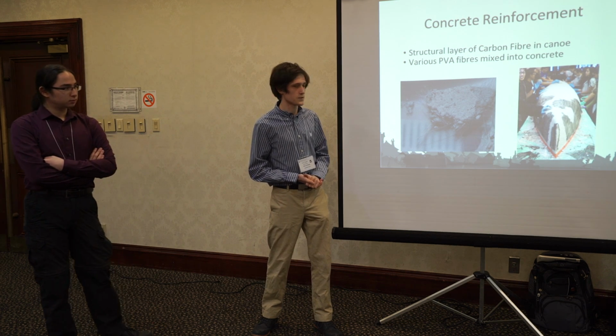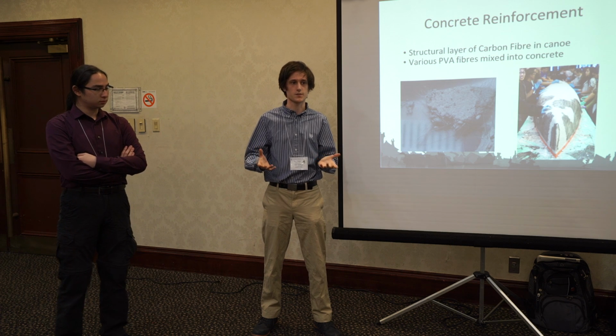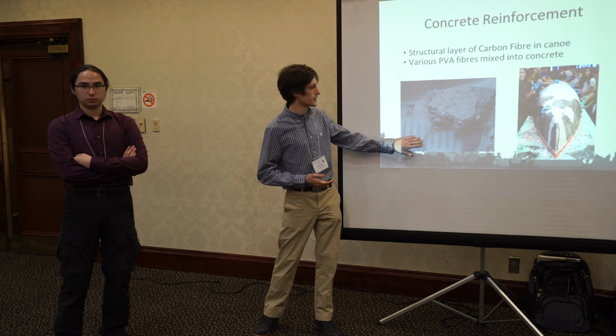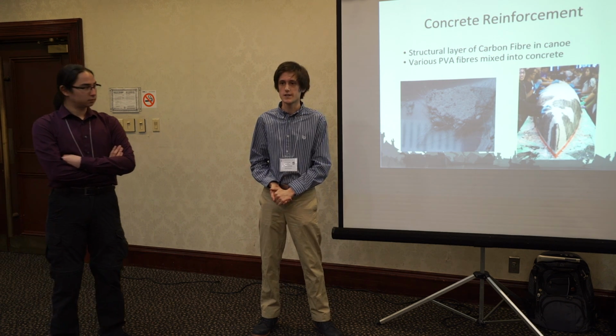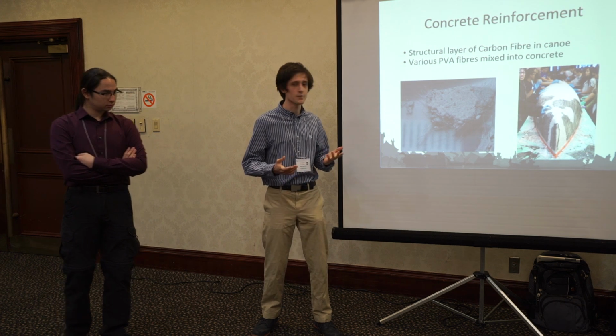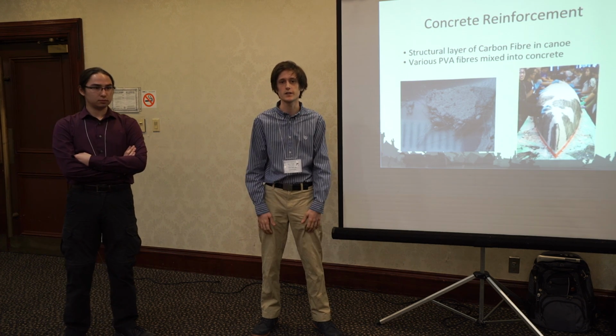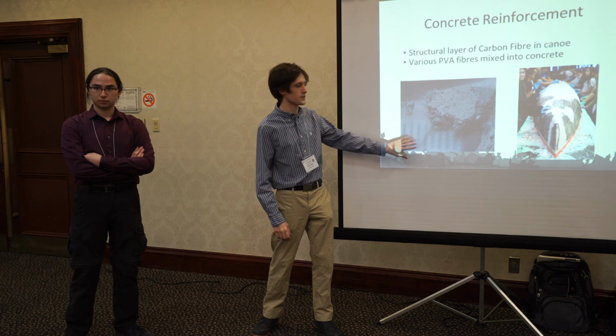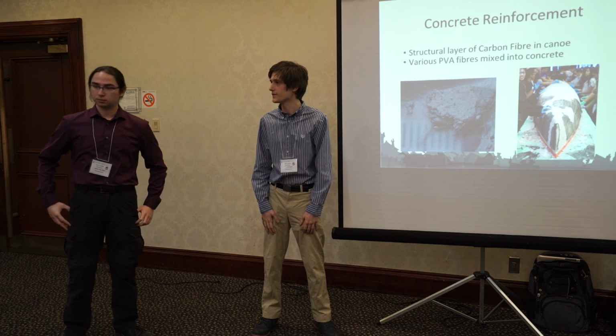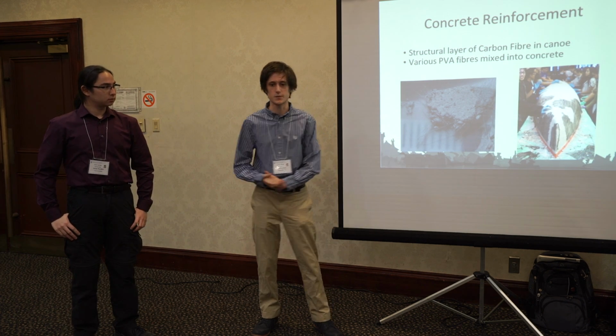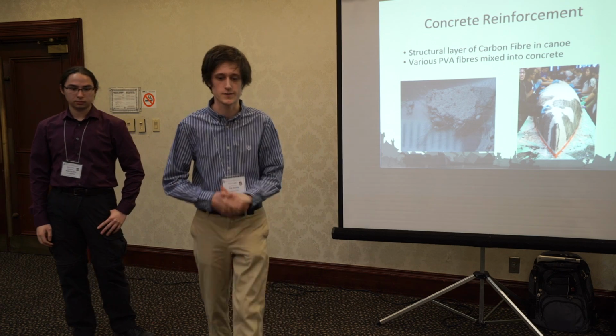On top of that, within the structural layer of concrete, what differentiates the structural from the finishing layer is we put in some PVA fibers. The idea behind this is if you put in a random matrix of fibers and you try to pull the concrete apart, it puts a lot of the tensile force onto the fibers rather than the concrete itself. So through these innovations, we can improve the strength of the concrete significantly.